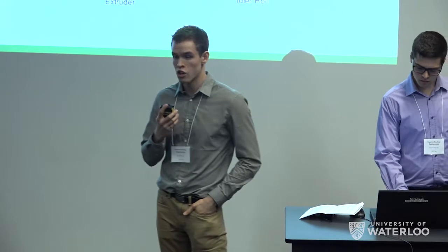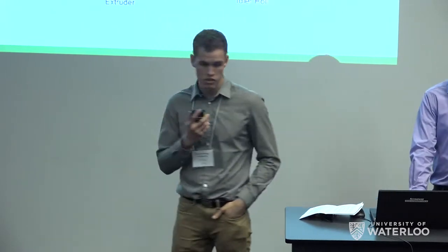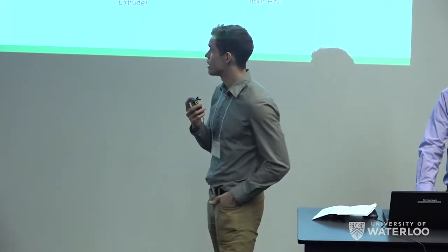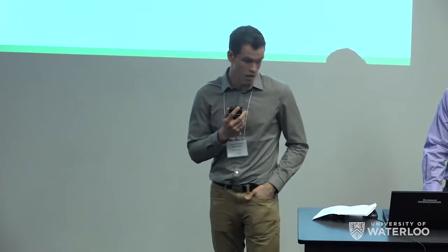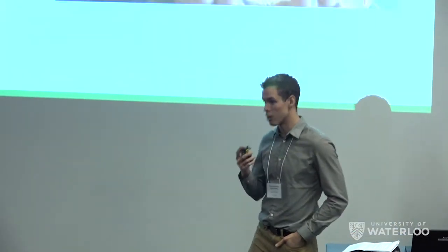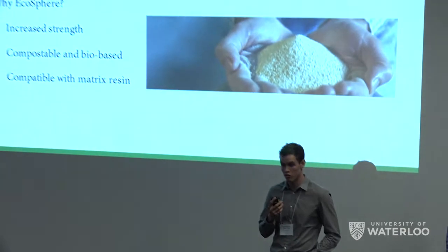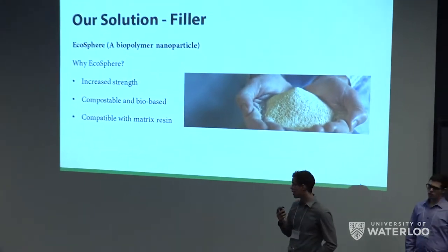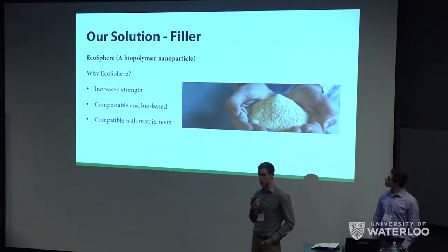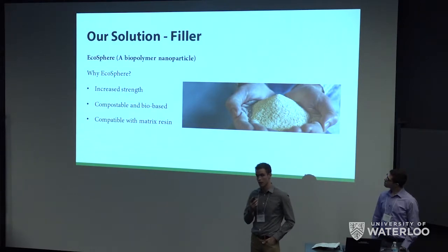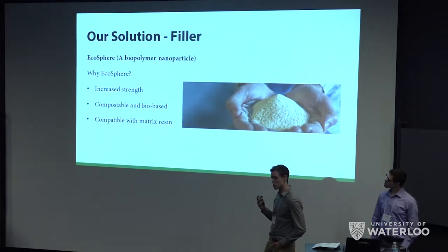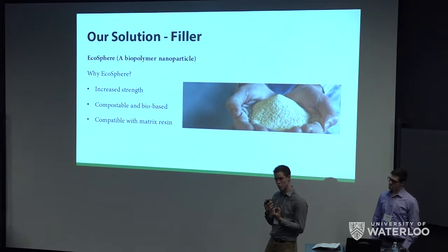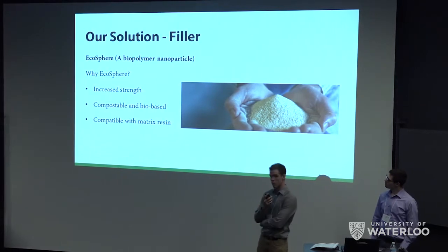Nanoparticles, on the other hand, do work pretty well with this process, so we ended up deciding on using EcoSphere. This is a nanoparticle, or a biopolymer nanoparticle, that is created out of maize starch out of Guelph. A few of the good properties is that it increases the strength as we incorporate it into the matrix. It induces crystallinity as it acts as a nucleation point, and it is compatible with matrix resins.